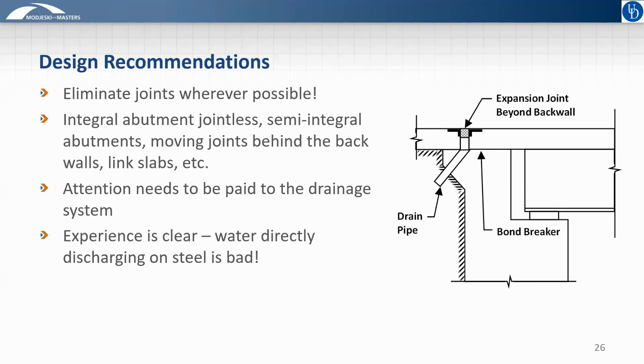So if there's nothing else you remember from this portion of the presentation, it should be this, and that's eliminate joints wherever possible. The experience is quite clear. Anytime you have water directly discharging onto steel, you have poor performance, whether that steel is painted or uncoated weathering steel. So the use of integral abutment bridges, other types of jointless bridges, semi-integral abutments, moving the joints behind the back walls, using link slabs, anything you can do there to eliminate joints is really the best thing that you can do in terms of extending the lifespan, really, of any kind of bridge, but in particular for uncoated weathering steel.